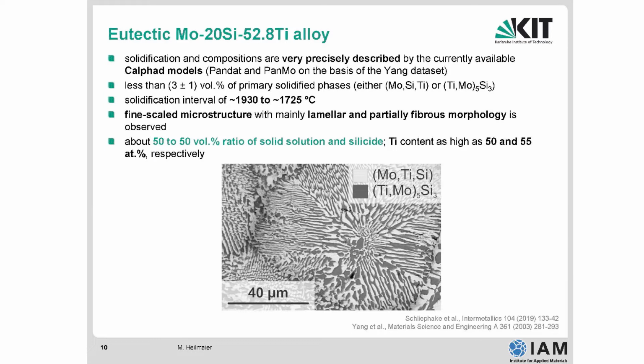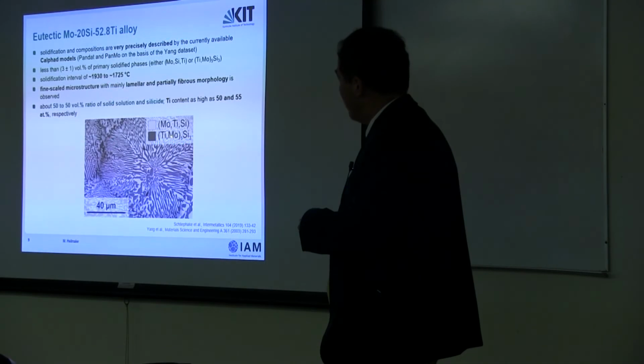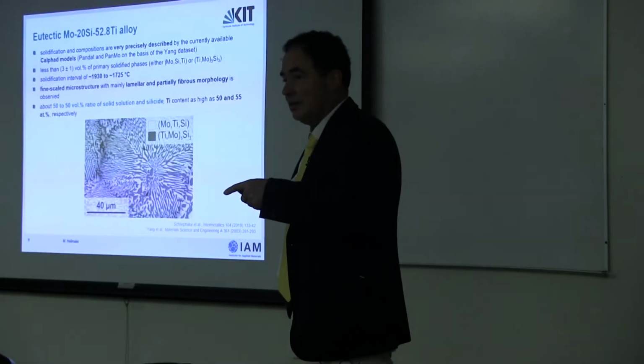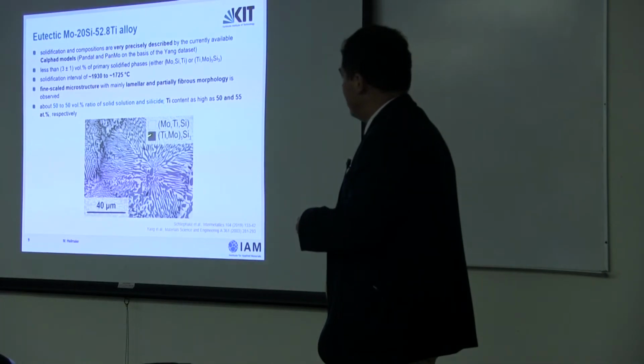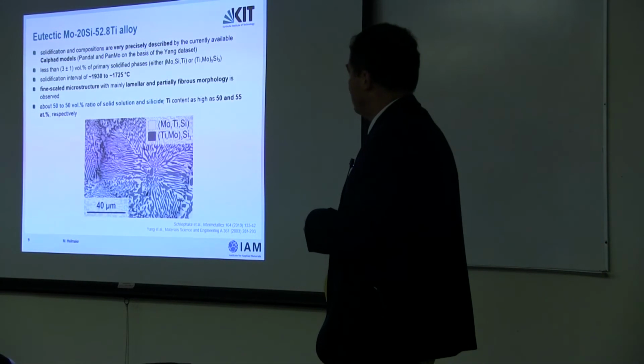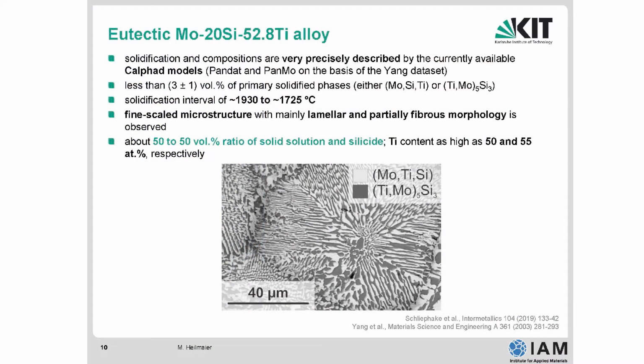Okay, so we, of course, did some calculations. I don't want to stress you too much with details here, but the eutectic transformation depends, of course, strongly on the chemical composition. For this particular alloy, the melting point is on the order of 1900 degrees Celsius, so pretty high compared to the nickel-based superalloy. And we get a very fine-scaled microstructure with these lamellae here. This is the scale bar here, 40 microns. This is still a scanning electron micrograph. And of course, the dark phase we determined by EDX and other methods is Ti5Si3 together with some molybdenum, which assumes titanium sites in the crystal structure. And the light phase is mostly molybdenum plus some titanium and silicon. Okay, so for the moment, keep that in mind.